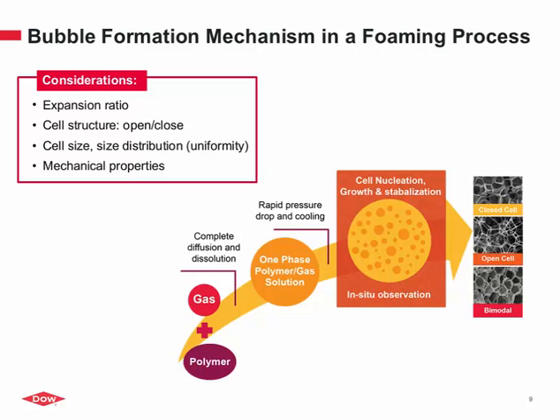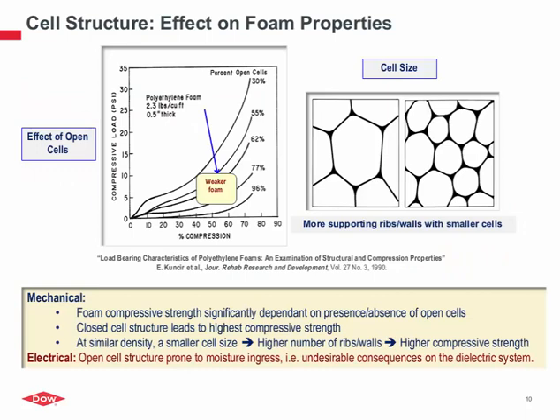And if we go to the next slide, why is this important? The cell structure, that is. Actually, this is work from a completely different field than ours. However, it's quite relevant, and what is shown here is the compressive characteristics of foams. It's a polyethylene foam, and depending on the amount of open cells present in this foam, as you can see, the compressive strength is quite drastically affected. Essentially two factors matter: the open cells and the cell size. And graphically here, the cell size, on the other hand, affects the compressive strength, as you can see.